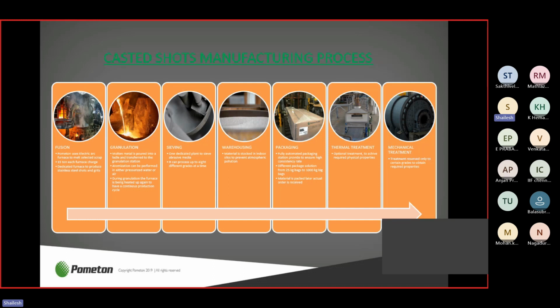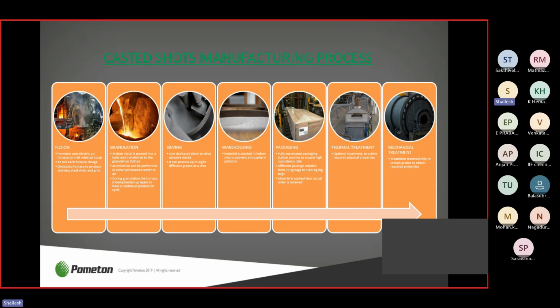After granulation, the shots are put in a water bath where they are kept for some time, and after that they go for drying, and then to the sieving station. In sieving, we segregate the different sizes of shots manufactured during granulation. In the granulation process, we get different sizes of shots, not one particular size, so we have to sieve and separate all the sizes according to the requirement of the industries. After sieving, the shots are kept in silos in a warehouse to avoid atmospheric pollution. After warehousing, certain grades of shots require thermal treatment.